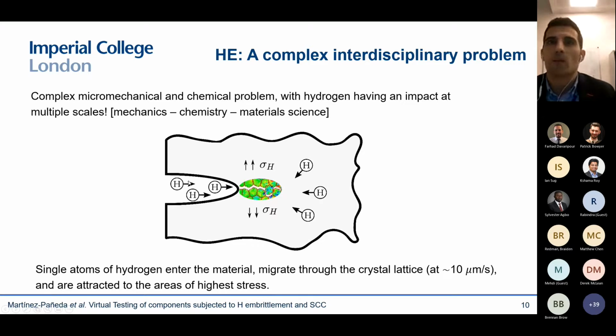So we do know the basics. We know that hydrogen atoms enter the material, they migrate through the crystal lattice, and they're attracted to areas of high hydrostatic stress or high volumetric strain, where there's more space for the hydrogen to fit in. However, then hydrogen in the fracture process zone interacts with the material in many different ways and at multiple scales. And this is quite a complex process. It changes the bonding strength between metal atoms, it changes the dislocation mobility, it facilitates the creation of vacancies. So there are multiple effects happening here, and the physical picture is complicated.